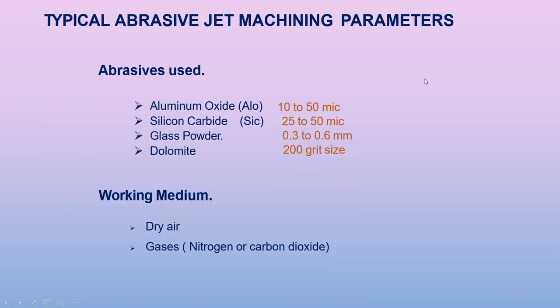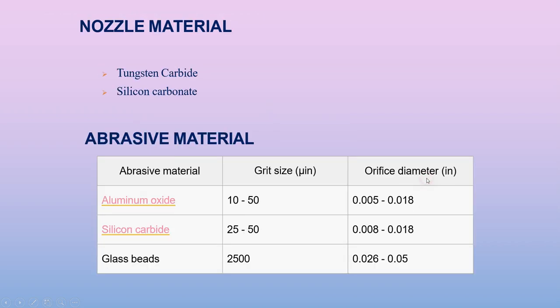So these are all the abrasive jet machining parameters. So the abrasives used normally are aluminum oxide, which is 10 to 50 micron, and silicon carbide 25 to 50 micron, glass powder 0.3 to 0.6 mm, and dolomite is 200 grit size. And normally the working medium here is dry air, and gases may be nitrogen or carbon dioxide.